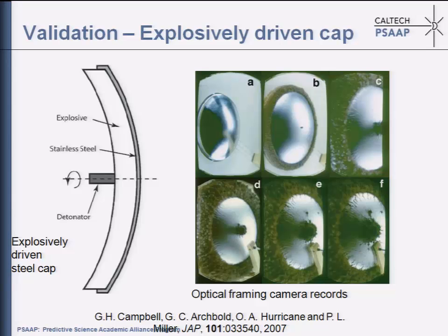Okay, so just to give you an example of the kind of predictive capability that we can get in the area of fracture. This is a very nice set of tests that were run at Lawrence Livermore by Jeff Campbell and co-workers. What they did is they took a spherical shell made of steel, and they blew it up. They detonated some high energy material on one side of the shell, and of course the detonation causes the shell to break up and undergo fragmentation, in fact, fine fragmentation.